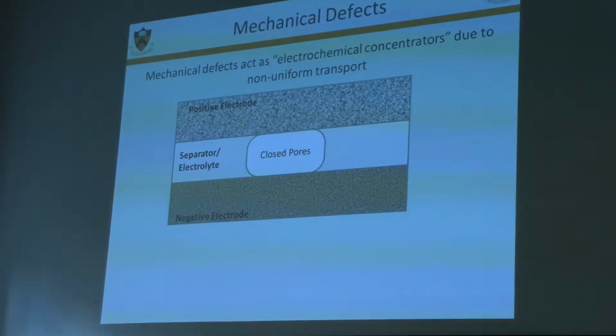Okay? So that says we're getting closer to understanding what's going on. Okay, there's something going on with this pore closure. There's something that's happening when I squeeze this cell that creates some kind of reason for lithium to want to plate, not under the stress, but right next to where I apply the stress. So we can set up a model.